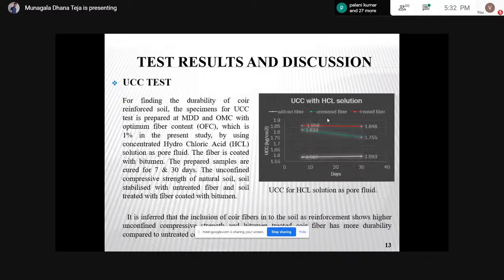Coming to the durability test, I did the UCS test. The gray color shows without fiber, the green color shows untreated fiber, and the red color shows treated fiber. Treated means I treated the coir fiber with bitumen emulsion. I did 7 days curing and 30 days curing tests and compared the results for 7 days and 30 days. It is inferred that the inclusion of coir fiber into the soil shows higher compressive strength, and also bitumen treated coir fiber has more durability compared to untreated coir fiber.